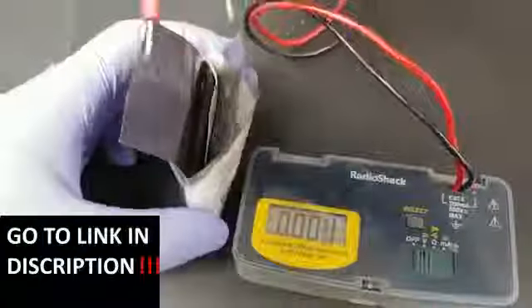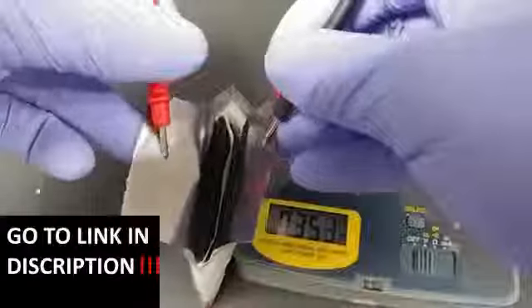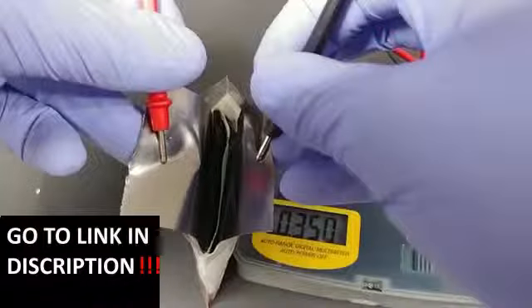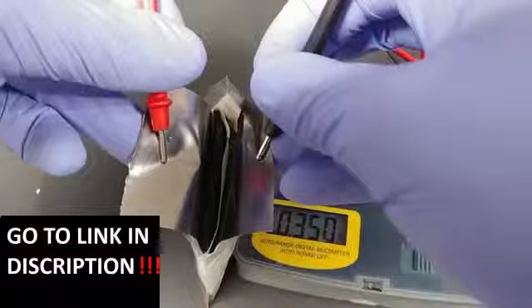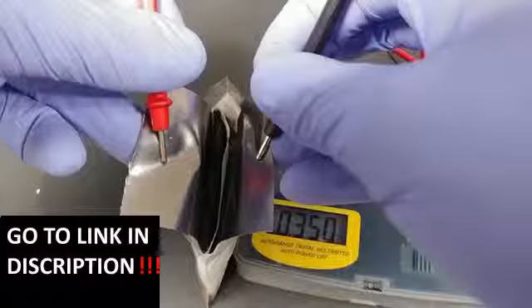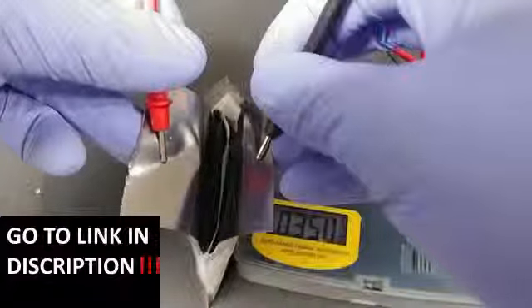Each cell is going to produce roughly 0.5 volts. Initially, right after hydrating, it starts off a little low, 0.35 volts, but after the electrolyte soaks through that separator, it increases modestly. And of course, it has a reasonably high internal resistance, and so you get a little bit of a voltage drop under load as well.